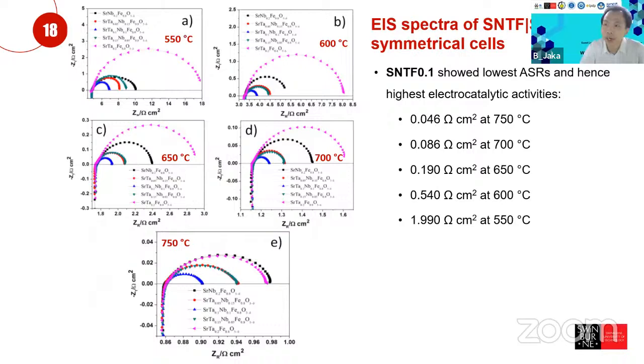Next, we also do the symmetrical cell test. Okay, we can see that the area specific resistance varies from 0.046 to 1.990 at 550 degrees Celsius. And this one is basically showing the comparisons for all the dopant components. So imagine that we are making 5 different symmetrical cells, and we tested them one by one.